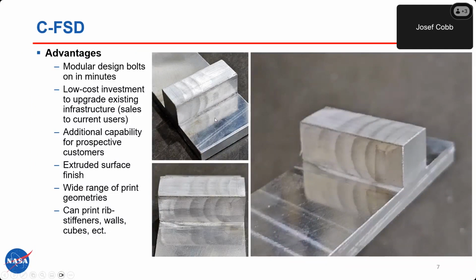But here is what that deposition looks like when you get done with the process. So this is as deposited, a 1/4 inch by 1/4 inch material deposition. And so this is as deposited. We get a really smooth surface finish. So there's no carbon in our deposition. We did have carbon previously, but we have since removed the carbon from the process. So it's just as deposited. This is a 2195 deposition onto a 2050 plate.